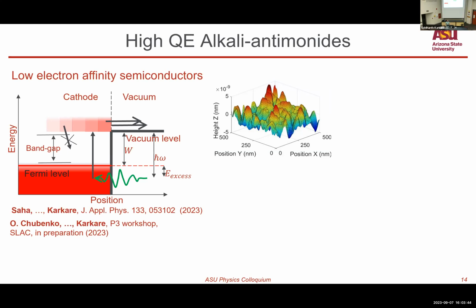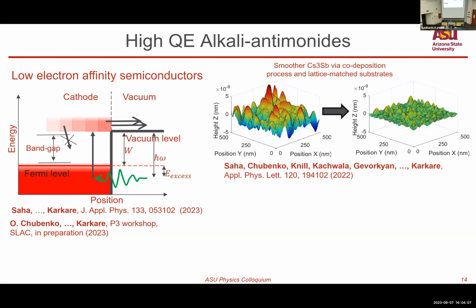So we put this rough surface in an electron gun. It creates transverse electric fields, increasing the mean transverse energy. We have come up with new growth recipes for these materials to develop a very, very smooth surface, a near atomic scale roughness for these materials. We modified the sequential deposition process into a co-deposition process where cesium and antimony are deposited at the same time, and that gives us a smoother film.